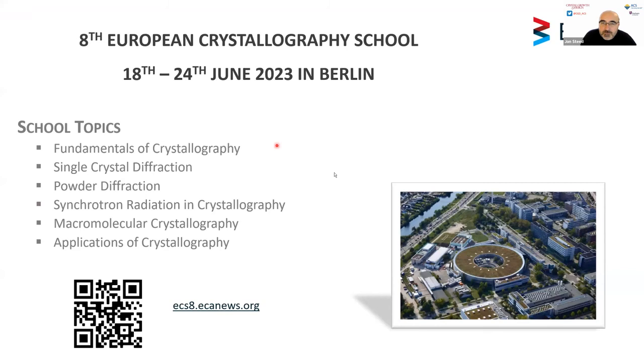Yeah, also if you stick to the ex situ regime, you also have to keep in mind that the sample that you measure maybe 2 hours later is not the one that has left the jar. So there are changes in between, and we have seen reports where people kept on measuring that transformations, once induced, would go on even without any impact being present anymore.